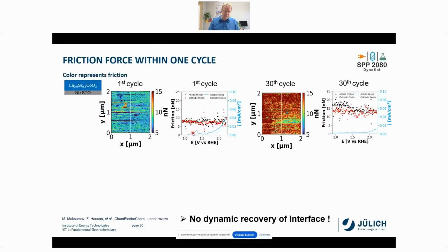And here you see something which we call a frictogram. So there we plot the friction values in the same diagram as the cyclic voltammetry. So we plot them on top of each other so that we can relate exactly what happens there. And then you see over the whole potential range, there's not much change in the friction. So we can say, although we are cycling the material, there's no recovery of the interface. And in this case, the color represents again the friction force. So these are friction force images.